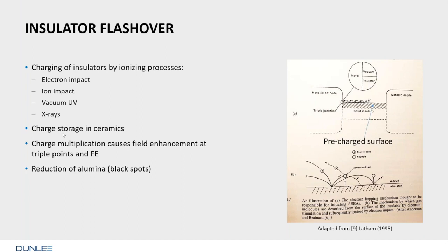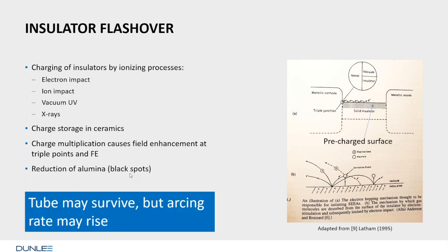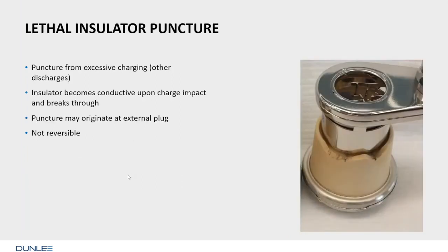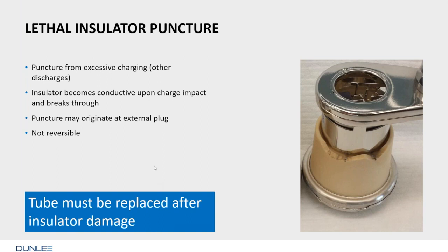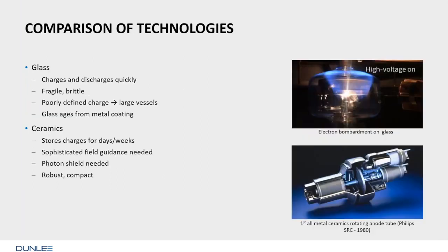It stores charge. So once the tube has a history of this, the ceramics is in a different situation than before. And charge multiplication causes field enhancement at triple points. And in the end, a flashover ends up with a reduction of alumina. You have aluminum left and black spots or traces. So the tube may survive such a thing, but the arc rate may rise once a trace is on an insulator. So this thing is lethal. If an insulator is really punctured, we have to replace the tube. The tube must be replaced. It's not reversible.